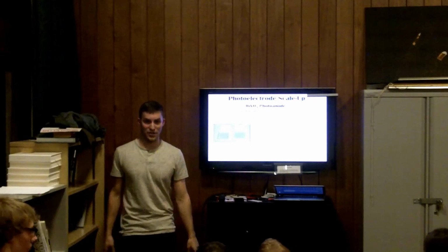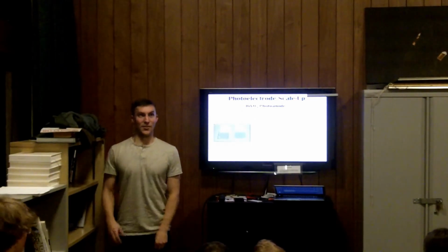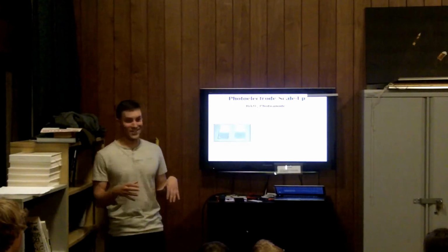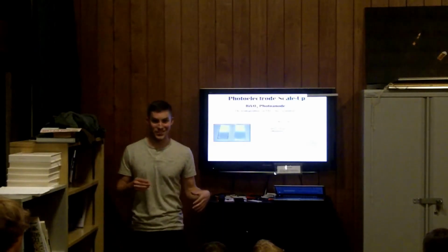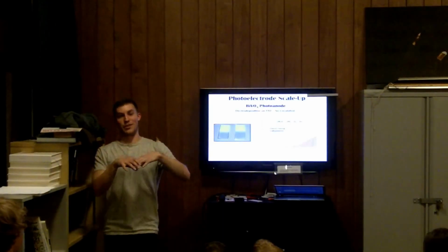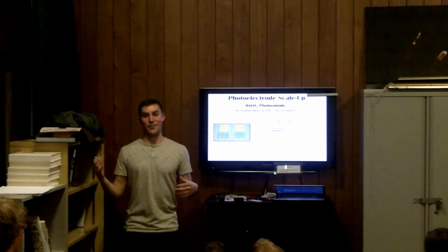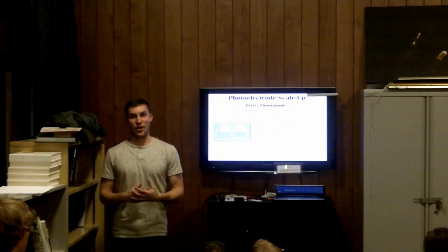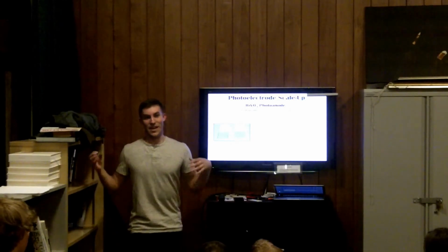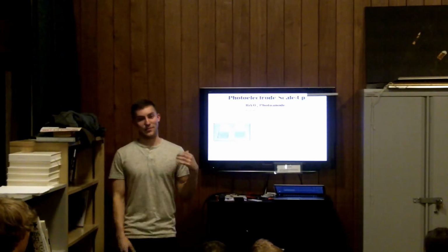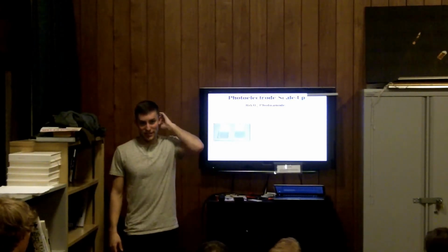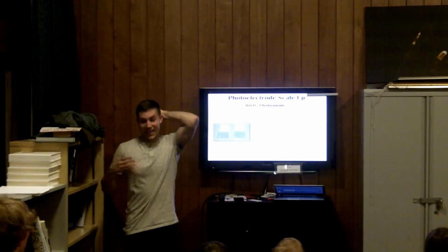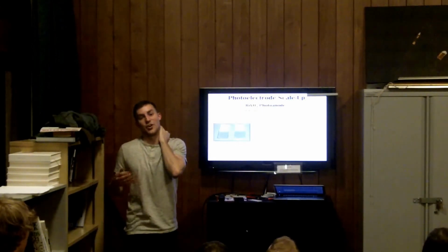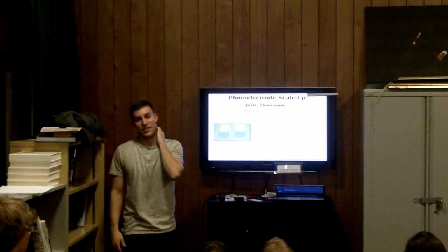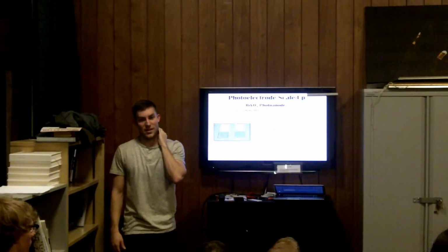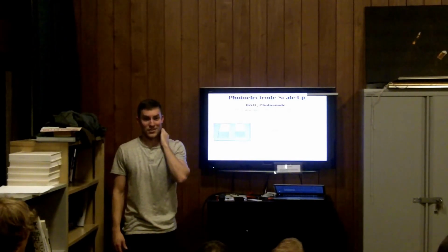And you're making these from solutions? The first step of the reaction is actually an electrodeposition, so that puts the bismuth precursor down on the slide. And then I'm using a solution that I drop cast containing vanadium, and then annealing them together to make the final product. Okay. So the second solution that has the vanadium in it, I'll just alter the ratio of the chemicals I use. That's the approach. We'll see if it works.